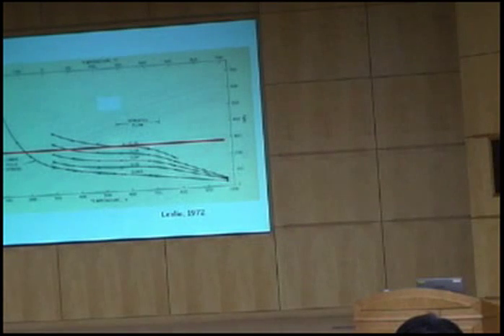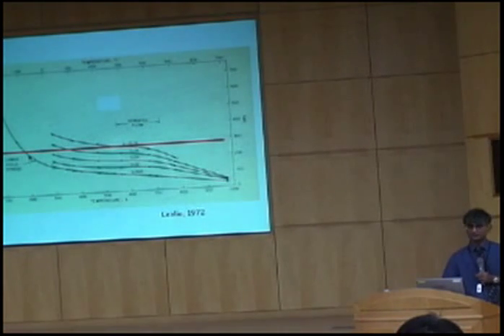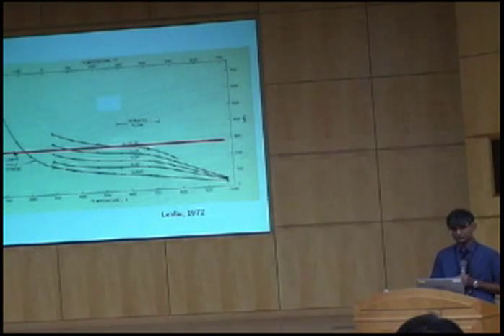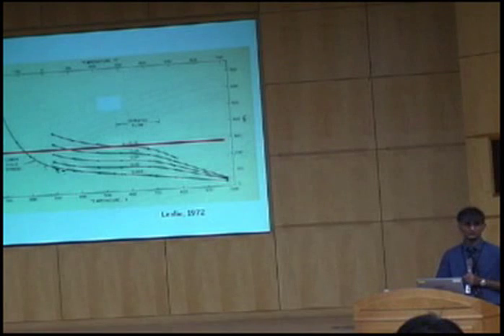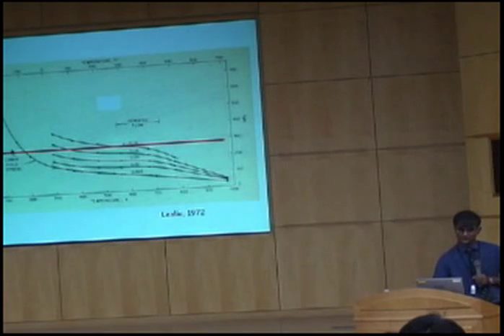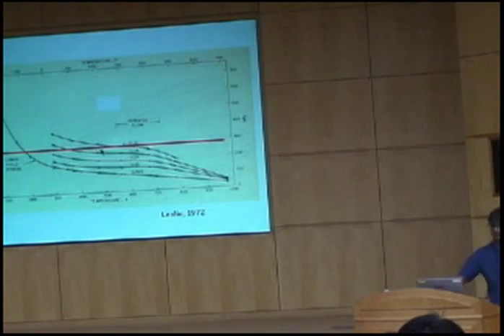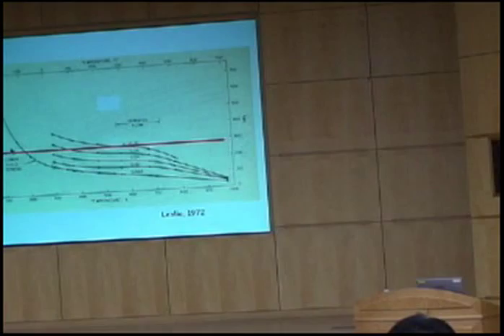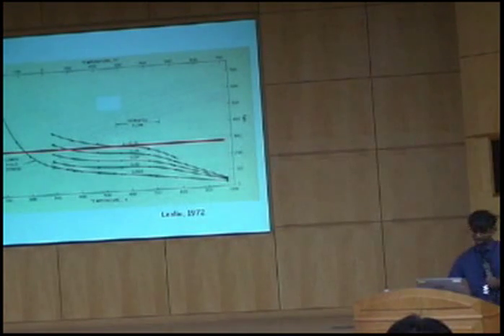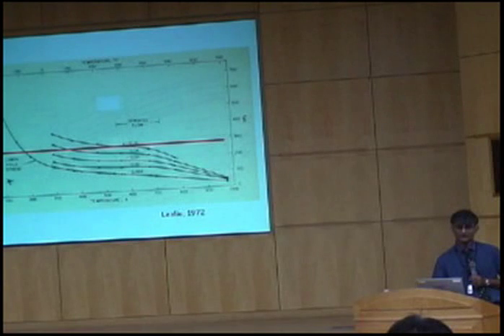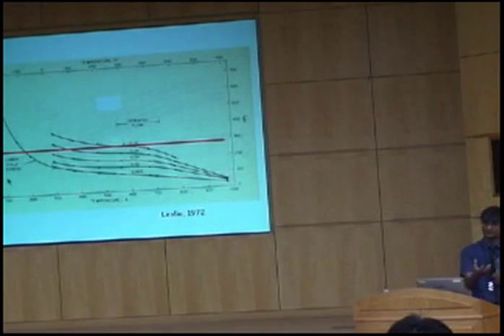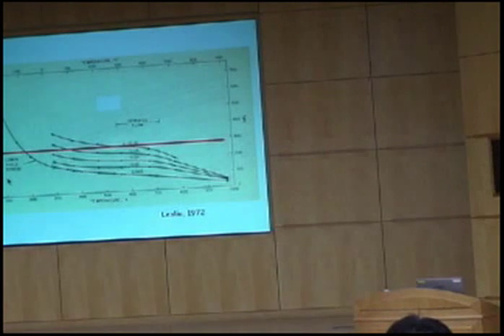Where those two curves cross at this point here is what we call the ductile brittle transition temperature. So below this temperature you have cleavage fracture, brittle fracture, and above this temperature it's easier for the material to flow by plastic deformation, so it is ductile fracture. The cleavage strength is not very sensitive to temperature, but the flow stress is very sensitive, and that is why we get a ductile brittle transition in ferritic iron. If this was austenite, then the flow stress curve would remain below the cleavage strength. So austenite doesn't cleave. It doesn't have a ductile brittle transition temperature.